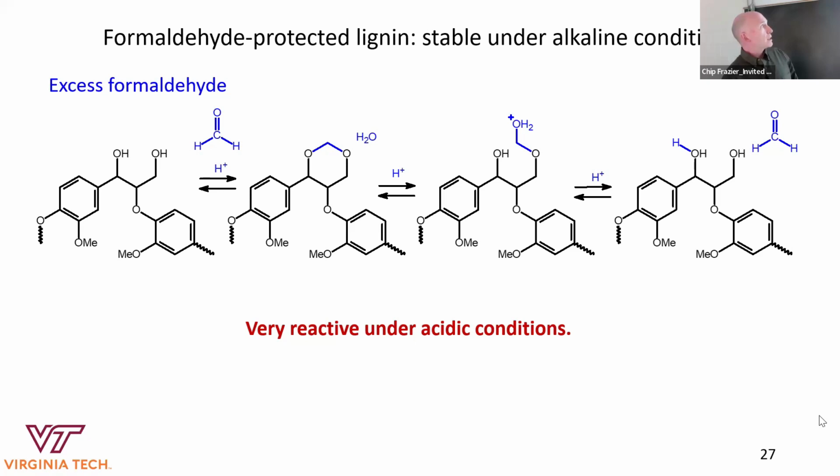But the reaction is then, once this opens, the lignin acidolysis cross-linking reaction that I mentioned. And also, if we consider the acetal transfer reaction, so if we have this acetal and we want to react it with another aldehyde, as I mentioned, the acetal has to break open so we can react it with another aldehyde. But at that moment, of course, lignin acidolysis could occur. So there's probably little doubt that by starting with formaldehyde and then switching to another aldehyde, the yield is going to be compromised because of this. You're going to reveal the native structure to some degree in an equilibrium. And if you do, it'll cross-link because lignin is incredibly reactive. Perhaps that is the best message from today, the one I'd like to emphasize. Native lignin is incredibly reactive, more so than I think folks have appreciated. So certainly more than I've appreciated.